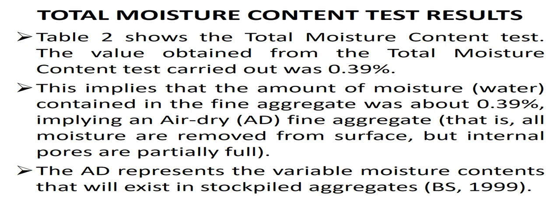Total moisture content test results. Table 2 also shows the total moisture content test. The value obtained from the total moisture content test carried out was 0.39%. This implies that the amount of moisture, that's water, contained in the fine aggregate was about 0.39%, implying an air-dry (AD) fine aggregate. That is, all moisture is removed from the surface, but the internal pores are partially full. The AD represents the variable moisture content that will exist in stockpile aggregates.